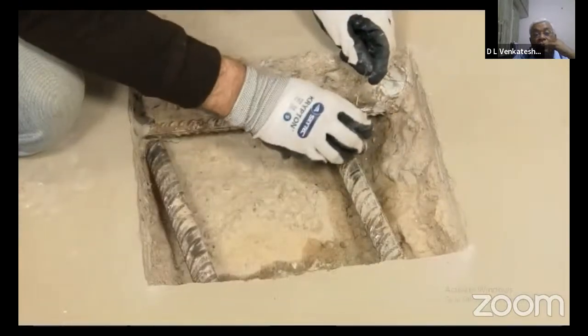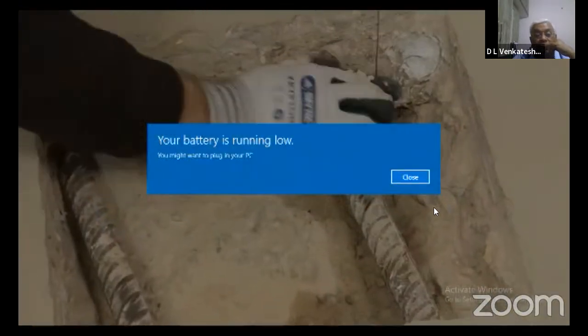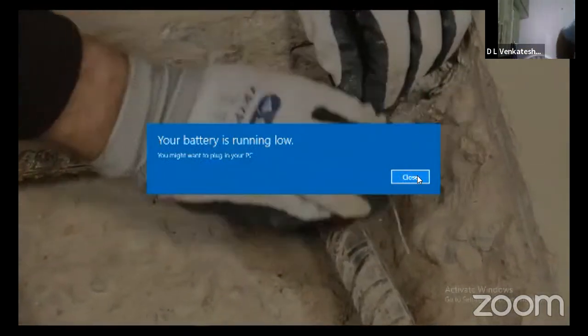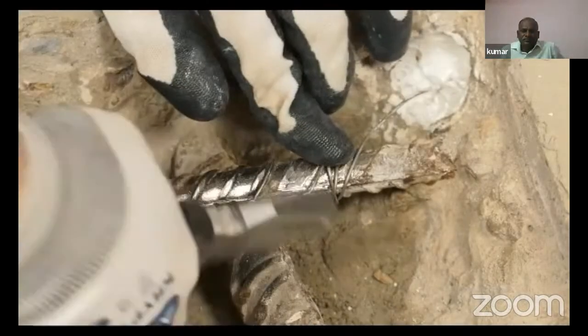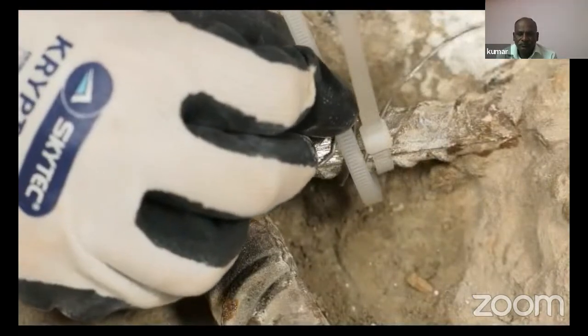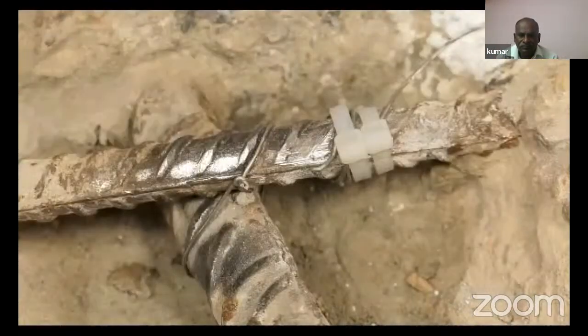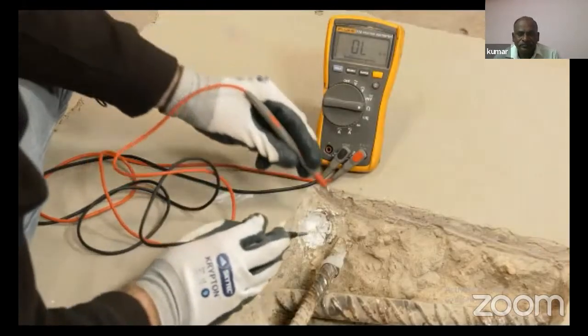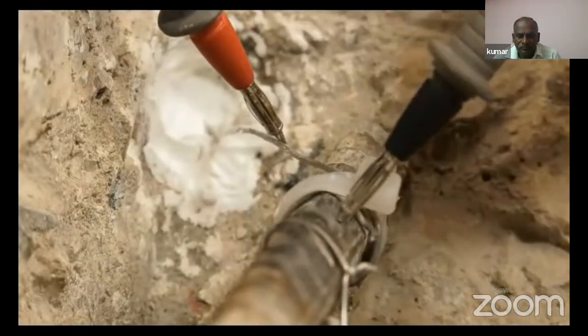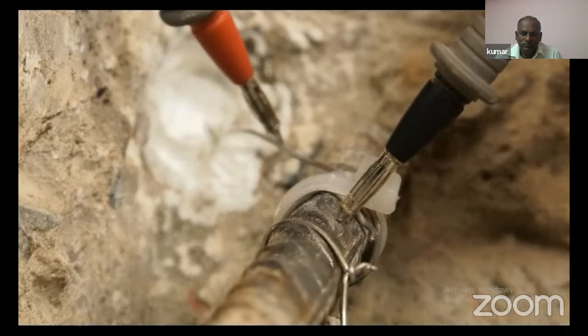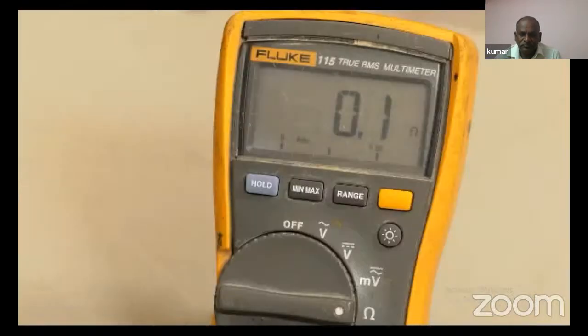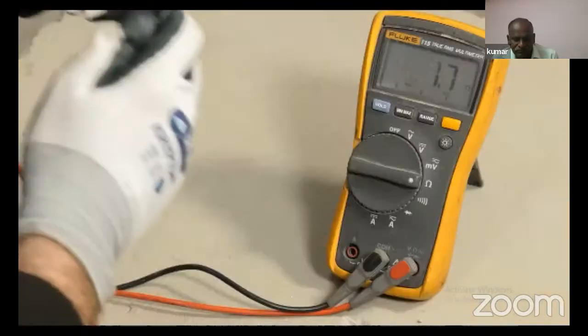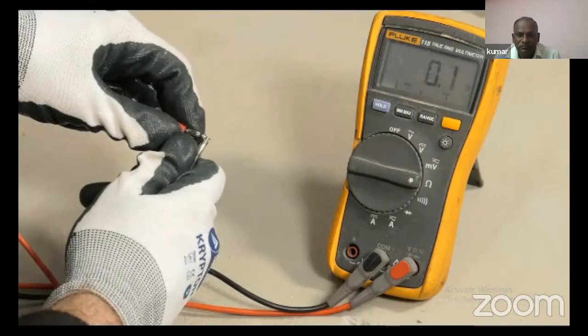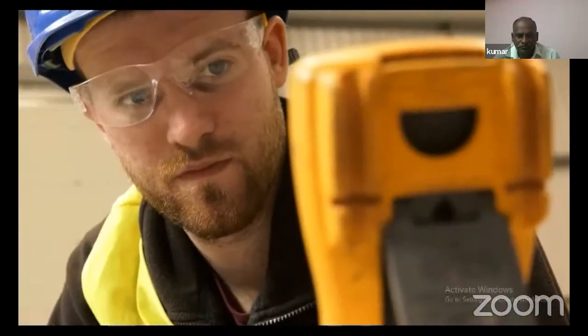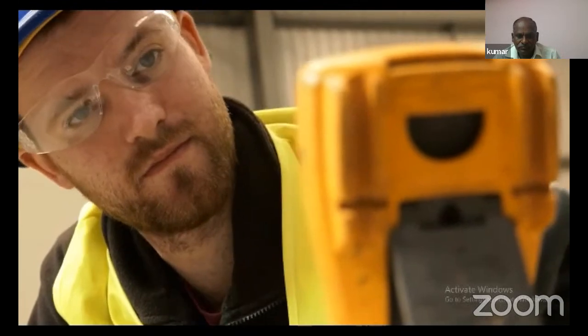Now securely attach the anode wire to the pre-cleaned steel surface using the two plastic cable ties provided. To ensure a good electrical connection, the resistance between the tying point on the patch guard anode and the reinforcing steel should be confirmed to be 1 ohm or less, using a suitable high impedance meter. Check the resistivity of your meter and cables prior to use and subtract this value from the figure that is read to give a true reading.